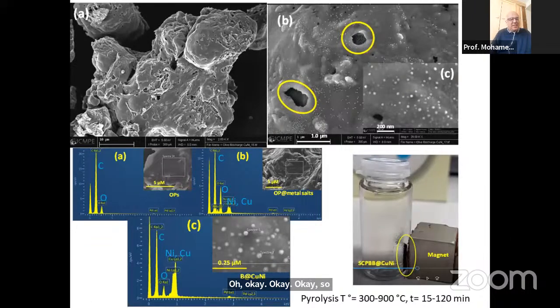Okay, so for example, this is with olive pit particles from biochar. It looks like a melted wax, not very porous. You can see some pores here, but you can see the nice distribution of copper nickel. We can of course monitor the surface elemental composition by EDX. We can see here the impregnation of the biomass with metal salts. We can see copper and nickel, and after pyrolysis there is less oxygen, of course, more carbon and more copper nickel.